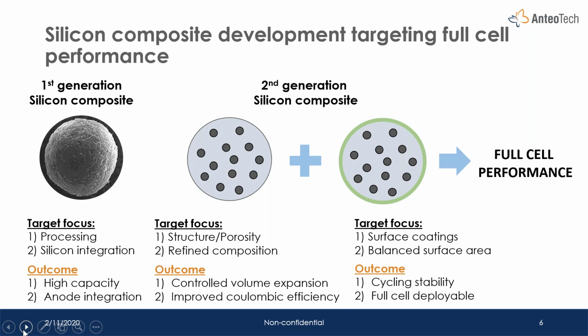So this slide shows our progression and our trajectory for our silicon composite development. Just to recap on the silicon composite and its purpose, it is an active material. It is actively storing lithium ions and charge in the anode. The objective is to drive up this charge storage capacity of the anode as high as possible, eventually leading to an anode capacity able to store more than 1,000 milliamp hours per gram of anode coating. Now, silicon does expand, and expands a lot, which creates a lot of issues and is responsible for the degradation of silicon during ongoing charge and discharge cycling.